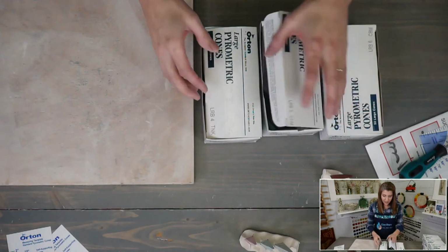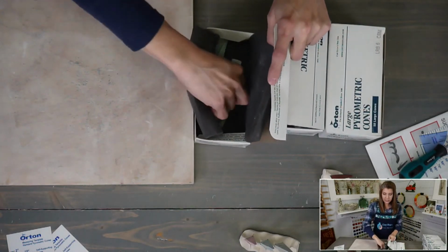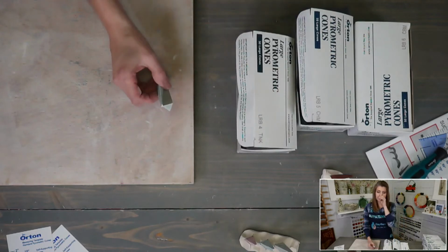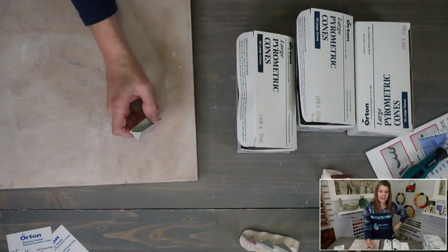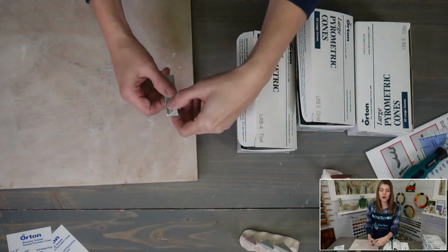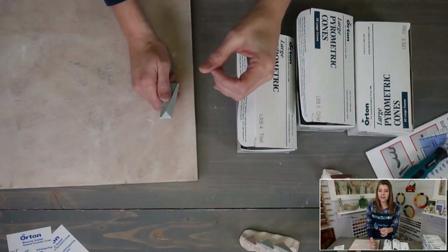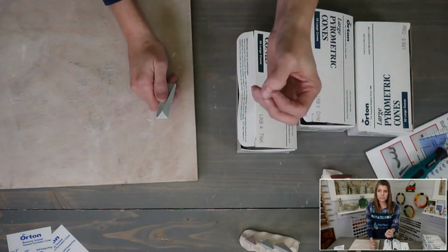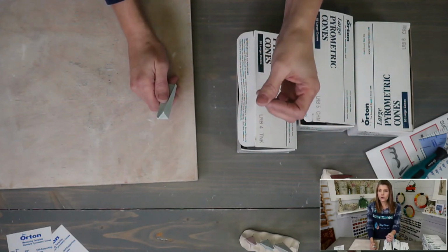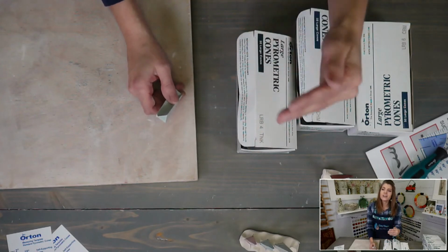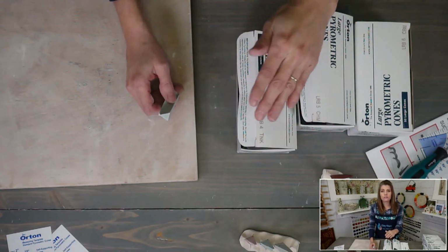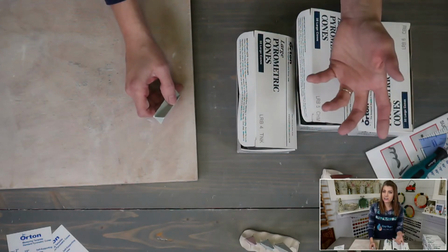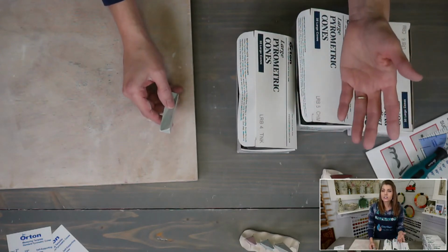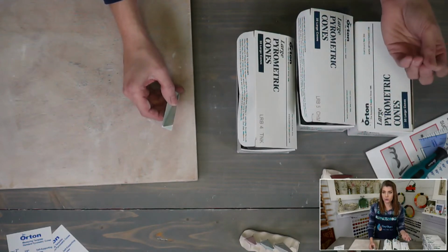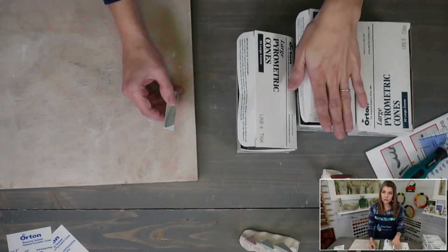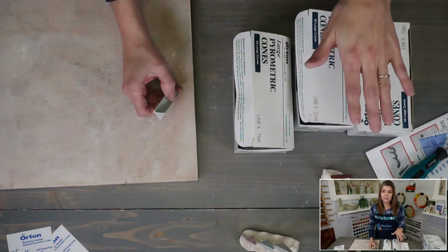Okay, so here we have our cones. And we're going to start, let's start with 4. So why do I bisque to 05, not 06? Jolene asked. So I bisque to 05 because 04 is a little hotter and it sometimes closes cone 5 clays up. I don't go to cone 06 because that's not quite enough and you can get more pinholing. By going to 05, it's burning off more of the organic matter in the clay, so you get less off-gassing during your glaze firing, less potential pinholes. So for me, with the firing to cone 5 glaze, an 05 bisque is perfect.